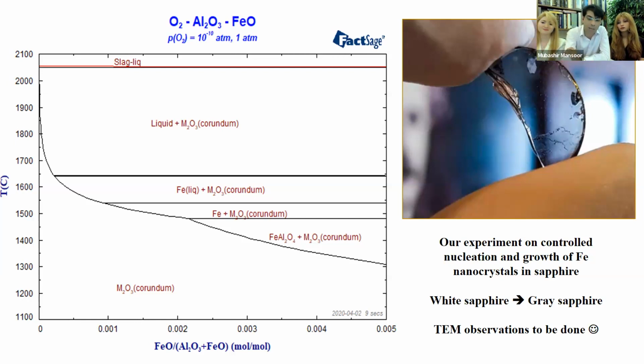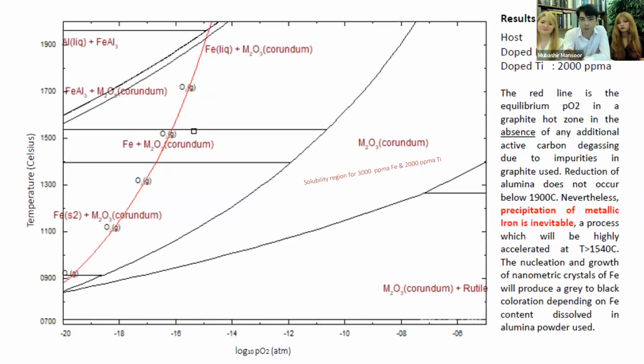Something else that I just want to emphasize, we did mention this, but it's very important to note. Look at this diagram here. It's telling us that even if you're at 900 Celsius, and you go down to about, let's say, 10 to the power of minus 17 atmospheres of oxygen, that means very little oxygen, you can, in principle, get complete dissolution of the rutile in sapphire. Now, that is alarming. Why?